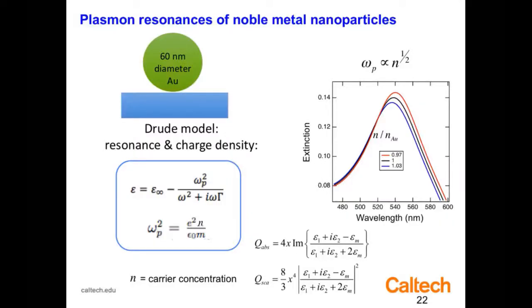So let's ask the question, how well could we tune a metal nanoparticle itself? A metal nanoparticle, as I mentioned, has a pretty high electron density, about one electron per unit cell, per atom. And you can see here how I could tune the extinction spectrum if I could change the metal nanoparticle carrier density by 3%. And I'll show you in a minute, that's about the limit of what we can do. You can see here, we can tune it a little bit. In fact, you can see that the peak is moving a little bit, and actually it's getting broader, more scattering of electrons on the surface. But it's fairly limited.